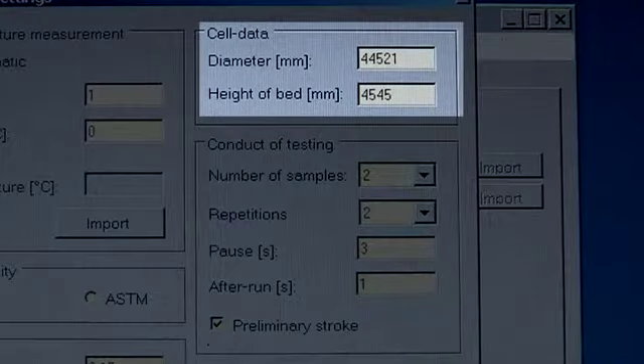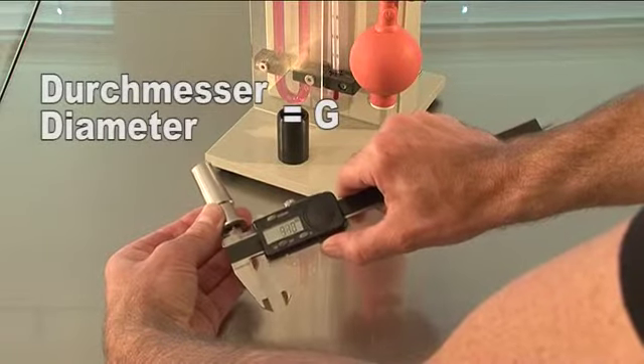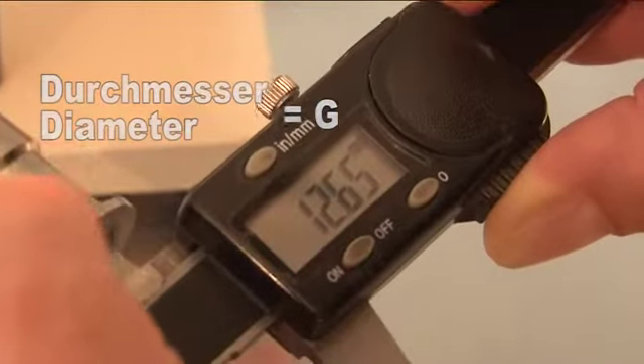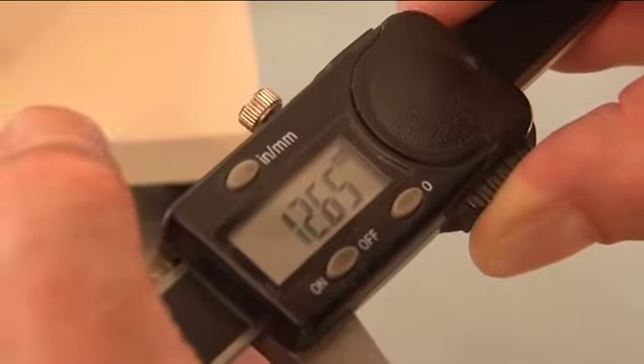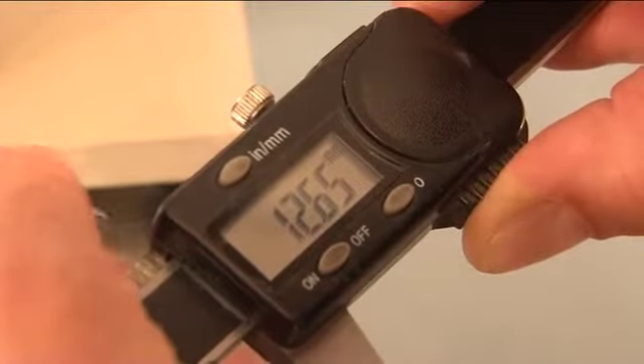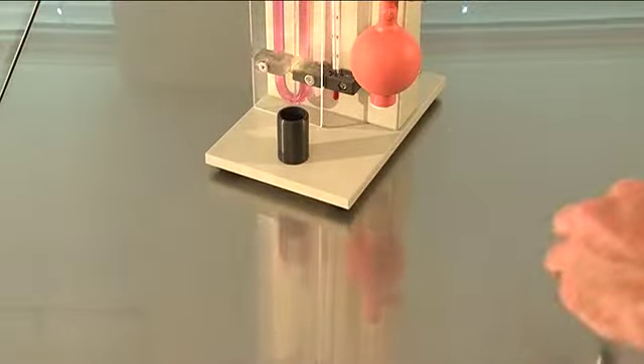Enter the inner diameter of the cell and test bed height of the sample in the field Cell Data. If these data are not known, the permeability cell must be measured with a micrometer gauge accurate to 0.01 millimeters. The diameter of the cell is determined at 6 different points. The mean value is established and entered in the computer field.